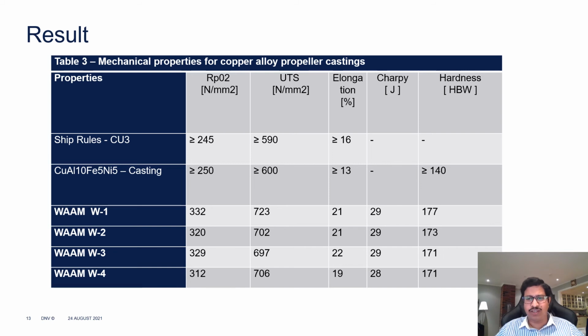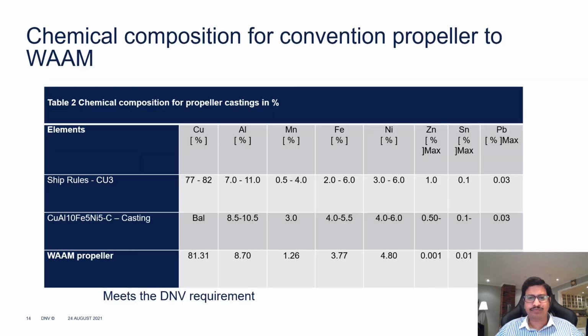And the Charpy test was done at 0 degrees centigrade to see if the toughness property is achieved, and the toughness was more than the required 27 joules. In addition, we have done a hardness test to see the comparative value, and it is also achieving the results of the casting. So in other terms, the mechanical results are, quality wise, more towards the casting side. We have also done a chemical analysis on the as-built part to check whether it is within the range of the rule requirement, and it also meets the requirement.